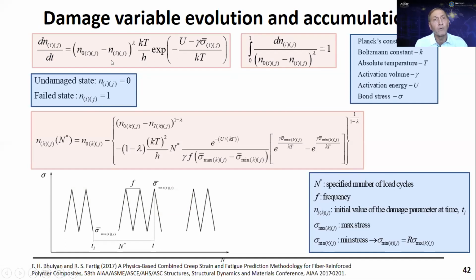So we have this evolution equation here. This is the activation energy. This is the activation volume. They come from the SN data. This sigma bar is the bond stress that you have. That's an equivalent stress. And so if you solve this differential equation subject to this constraint here, this lambda controls the shape of the damage evolution curve.